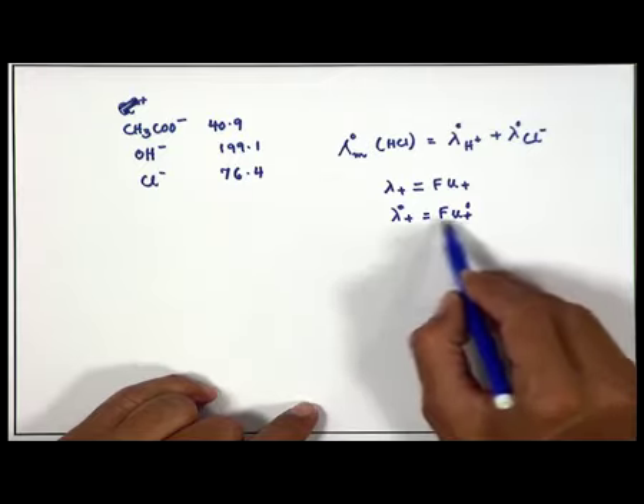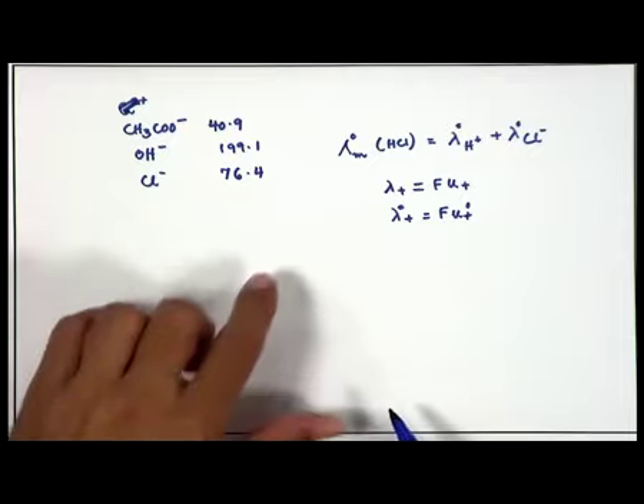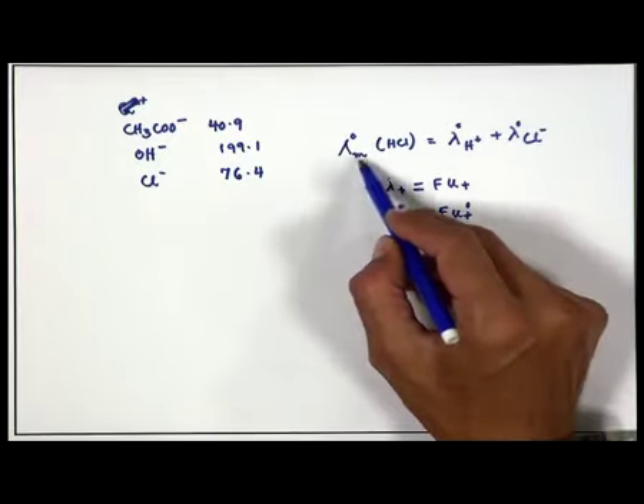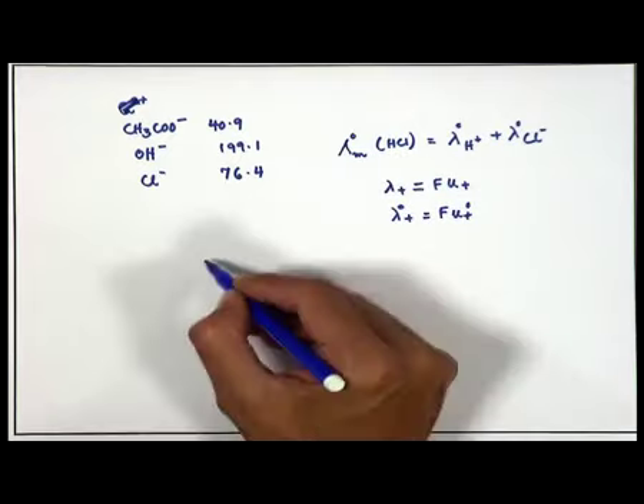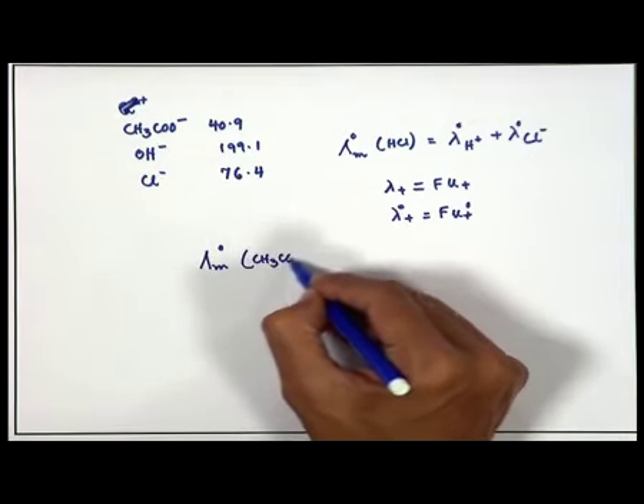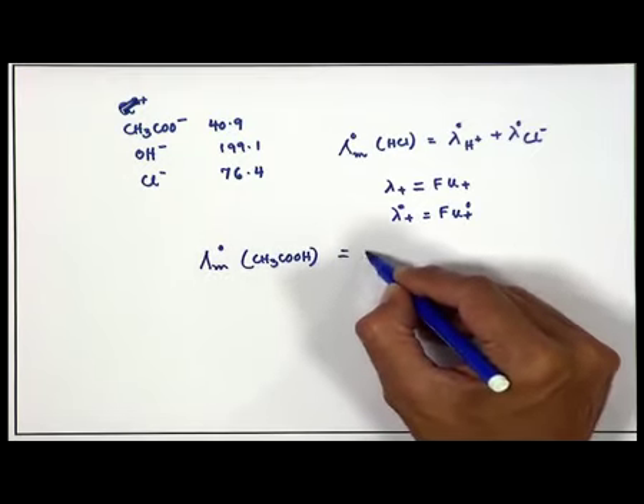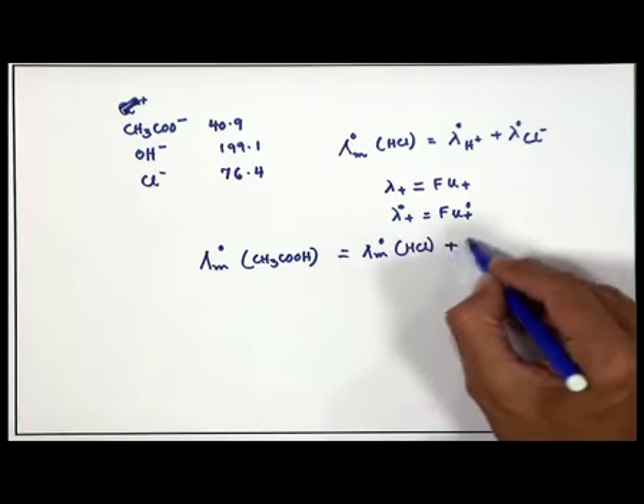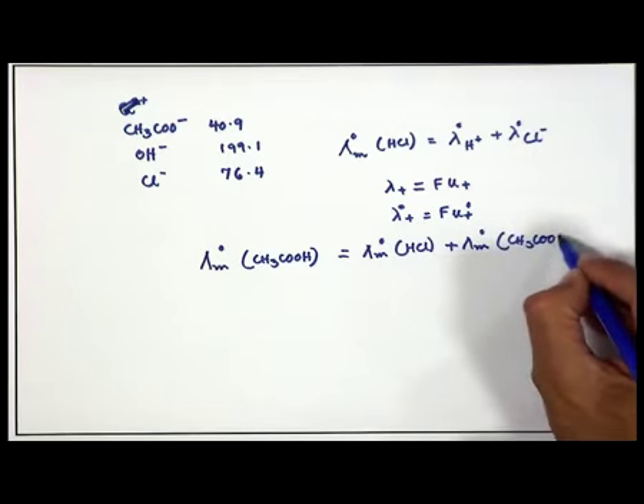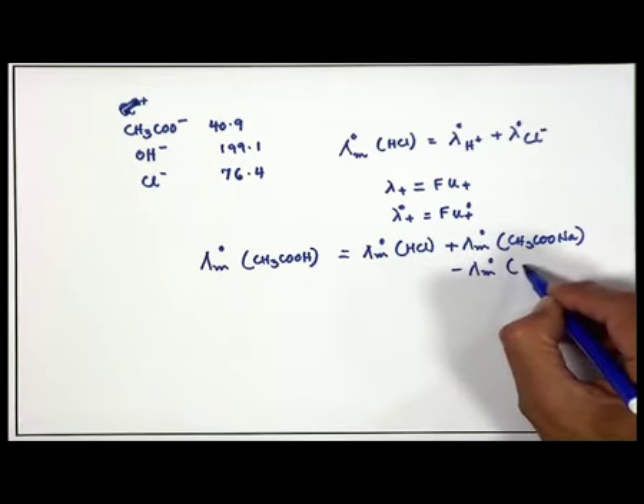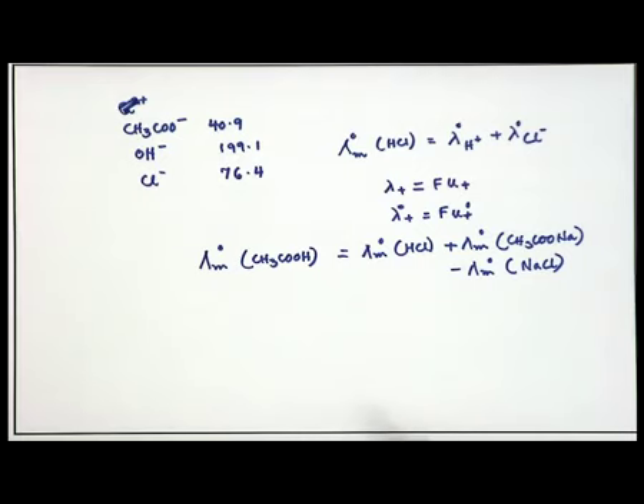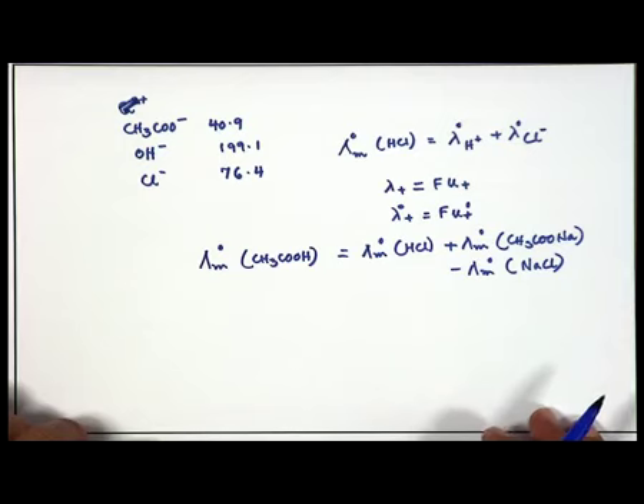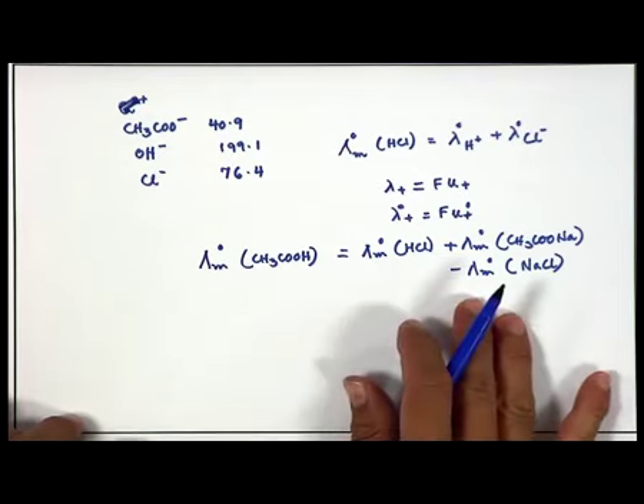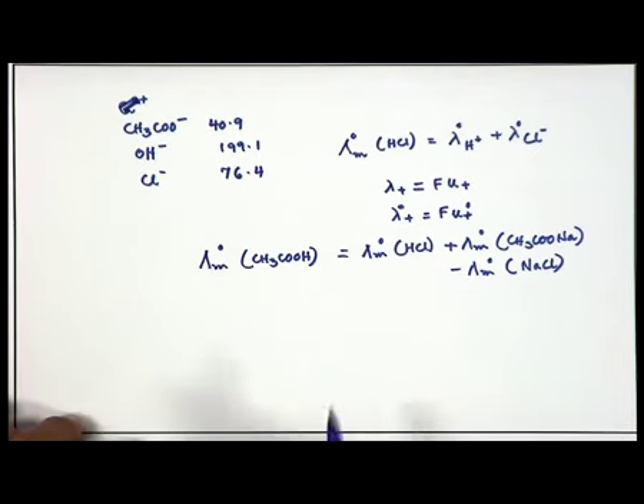So, this way you can find out these numbers experimentally, and then plugging in these numbers as per requirement, you can find out this lambda m 0 for different electrolytes. Therefore, for lambda m 0 CH3COOH, you are applying this Kohlrausch's law of independent migration of ions: lambda m 0 CH3COO minus Na plus plus lambda m 0 HCl minus lambda m 0 NaCl. Plug in the respective numbers and you should be able to find out this lambda 0 for the weak electrolyte. Direct determination of lambda 0 for a weak electrolyte is not possible, because the lambda m versus square root of C plot is not a linear trend. That is why you have to make use of this indirect method of finding lambda m 0 for a weak acid or weak electrolyte.